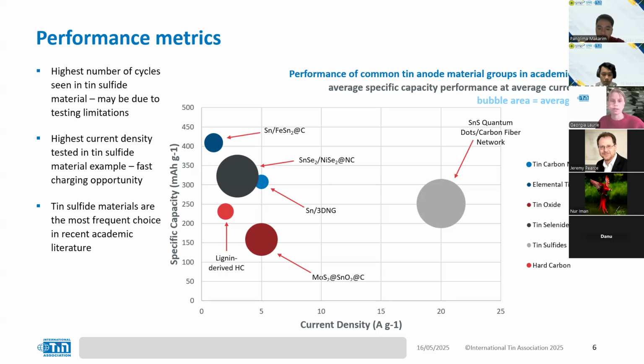On the graph as well, we have a hard carbon example here. You can see this red dot here, which is a lignin-derived hard carbon anode material. So I've just put this on here to compare some of the tin results with a carbon example, which is the most common anode material. So you can see that its position on the graph is a lower current density. It's a lower dot, meaning it's a lower number of cycles, and also it's a lower specific capacity than a lot of the other points. So its position on the graph really highlights the opportunities for high capacity, longer lifetime, and faster charging capabilities when using tin as an anode material.